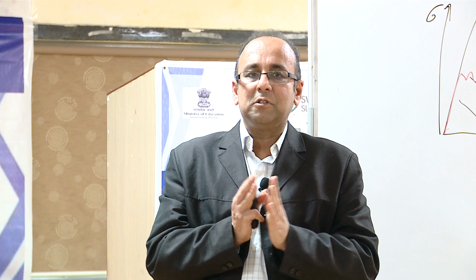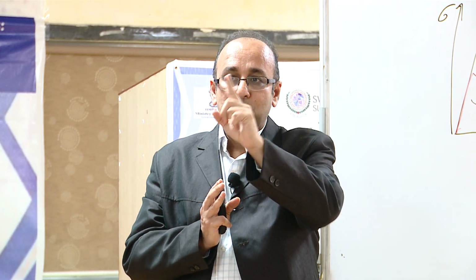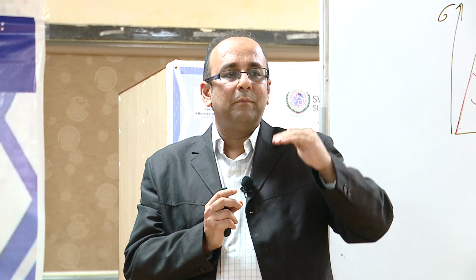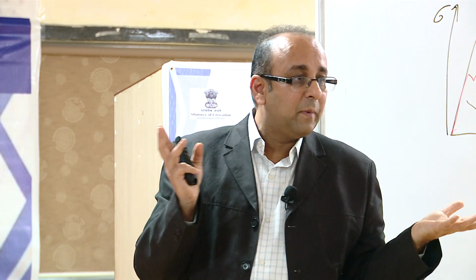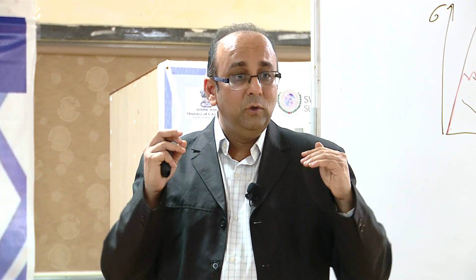Warm forming, as I told you, is very simple. You go into the austenite phase. Austenite phase begins at 723 degrees centigrade at the eutectoid point. But we are not working at the eutectoid point. We are working a little bit higher than the eutectoid point. So you have to increase the temperature, and we normally go to 950 degrees centigrade. At that temperature, practically everything turns to austenite. Means everything has FCC structure. Now this structure is a very good, deformable structure. You can give a complex part and everything, and then you cool that thing faster or intentionally slower.